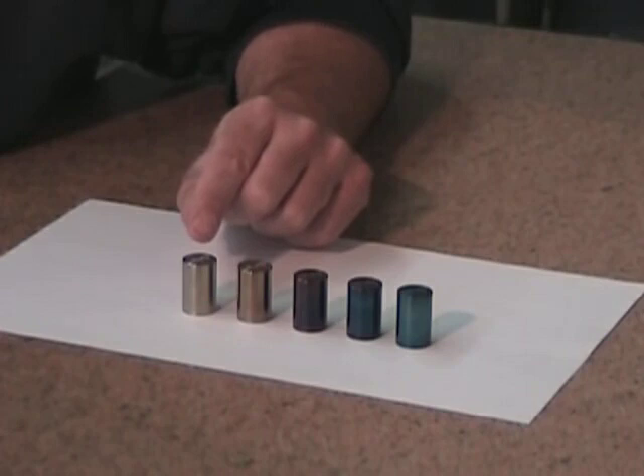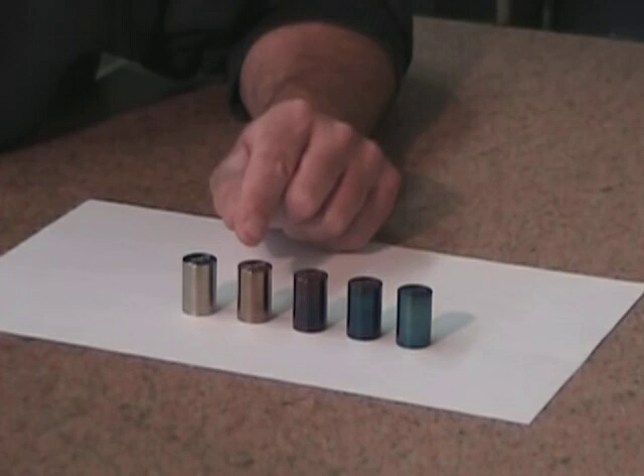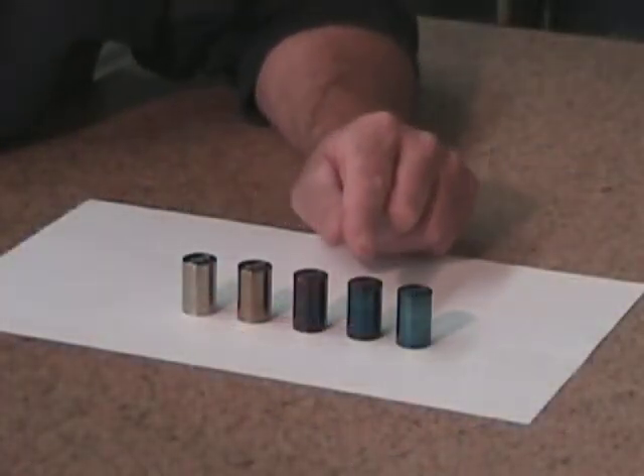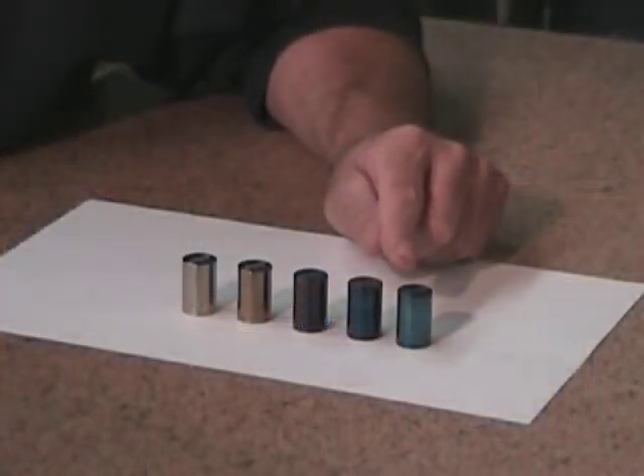Now, if you want just a light temper, you're going to look for our first example, 450 degrees, and it should become just a light pale yellow color. Something a little tougher, well, 500 degrees and a brownish tint would be what you're looking for. If you're into the purple zone, 530 degrees, the steel will be even a little tougher. 560 degrees gives us a steel that is quite tough, and it is usually the normal tempering temperature for most operations. Finally, 620 degrees will give you a very tough steel.